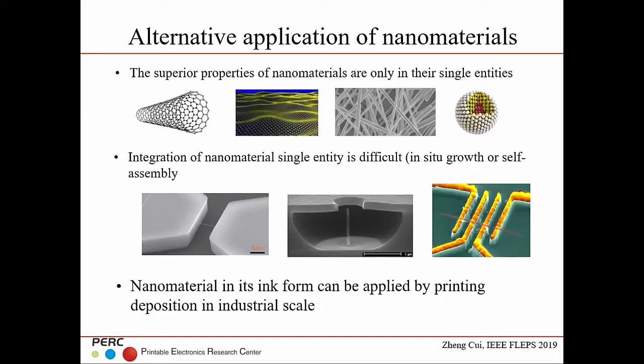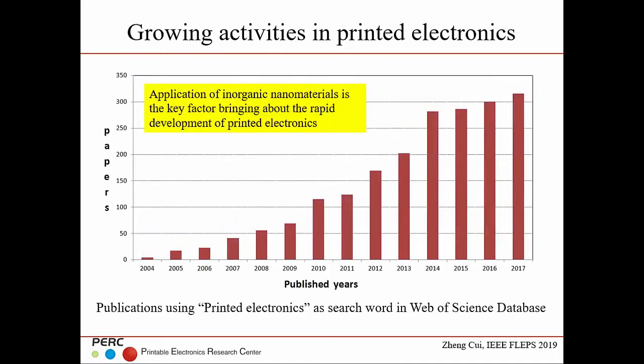But in fact, if you look at graphene, the most successful commercial product of graphene is making graphene powder, then you print it. That's the way to utilize the nanomaterial. And if you look at the printed electronics development, this is the number of papers published over the last 20 years. There's a significant increase in papers after 2010. And we guess the main reason is that inorganic materials started to be used as ink to print, which stimulated the development of printed electronics. The most prominent example is silver. We use silver nanoparticles to make ink, then you can print a wide range of conductive circuits.